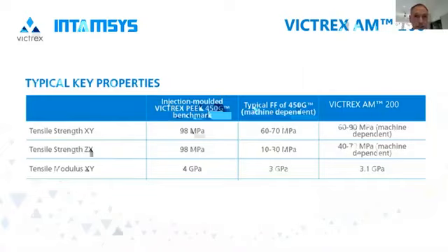So here we see some properties of printed AM200. The left column shows benchmark data for tensile properties, and this is the data from injection molded PEEK. So we're using this as, if you will, a gold standard, acceptable for all those applications I showed at the start of the presentation. The middle data shows typical properties for printed PEEK obtained on a range of machines from across the industry. You can see tensile strength in XY in the range here, 60 to 70 megapascals. For Z, 10 to 30 megapascals.